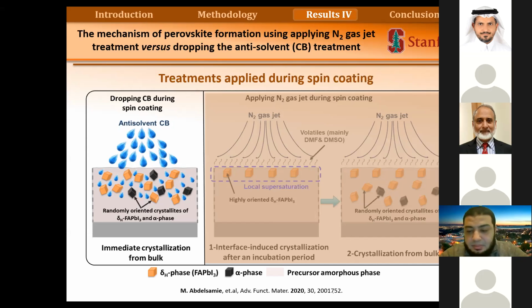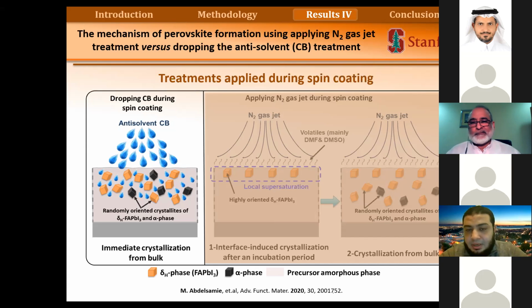Bismuth cannot directly replace lead because of the charge. The charge of bismuth is 3, and lead in this structure is 2. So you cannot just use bismuth, but you can use bismuth with another compound. You can have a double perovskite. For example, you can use silver bismuth. Silver bismuth will have the same charge as lead. So some people have done this, they use double perovskite. They replaced lead with two compounds, not just bismuth, like silver bismuth. So then you have the neutral charge.